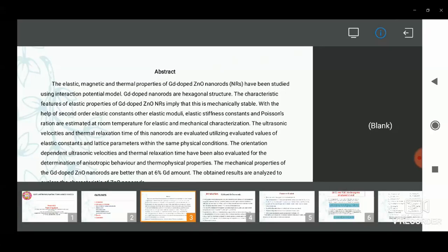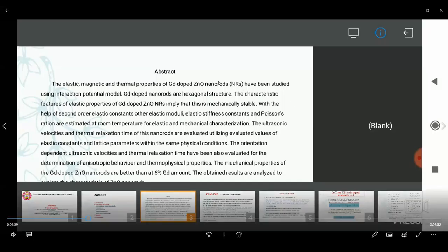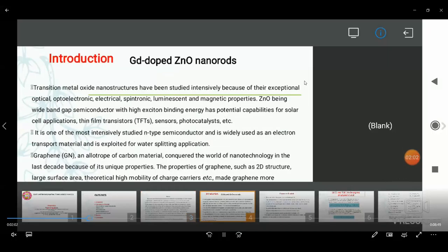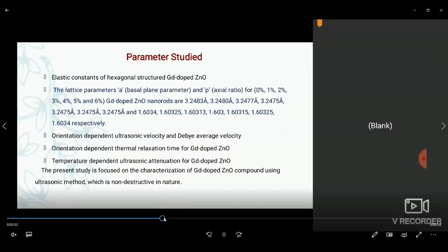The mechanical properties of the gadolinium doped zinc oxide nanorods are better at the 6% gadolinium amount. The obtained results are analyzed to explore the characterization of the zinc oxide nanorods. Transition metal oxides and nanostructures have been intensively studied because of their exceptional optical, optoelectronic, electrical, spintronic, luminescent and magnetic properties. Zinc oxide is a wide band gap semiconductor with high exciton binding energy and potential capability for solar applications, thin film transistors, sensors and photocatalysis. It is one of the most intensively studied n-type semiconductors.